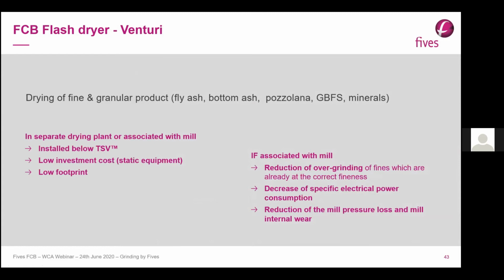The other system proposed by FCB is quite a more common example. It's the FCB flash dryer with a venturi shape of the duct. This is applied for fine or granular product up to 10 millimeter diameter, such as fly ash, bottom ash, pozzolana, slags, or minerals. In a separate grinding plant or associated with a mill, it is installed below the TSV. It has a low investment cost because it's static equipment with a low footprint.